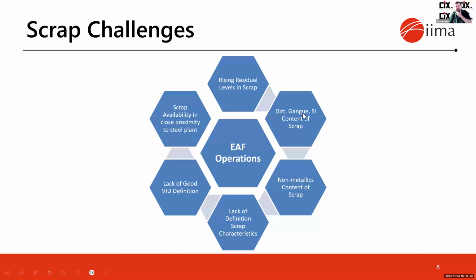So when we look at the challenges for scrap, rising residual levels is probably the biggest one. But then a close second is the dirt, gangue, silicon content of scrap. This contributes to the amount of fluxes that are required and has a huge impact on iron yield in the EAF. That's something that I'll dig into in more detail a little bit later. The non-metallics content of scrap, as one of my friends said, we need to stop using the EAF as an incinerator. What we want to put in the furnace is the Fe-bearing material. Anything else really contributes to either additional waste products, byproducts, or contributes to environmental issues in the operation.